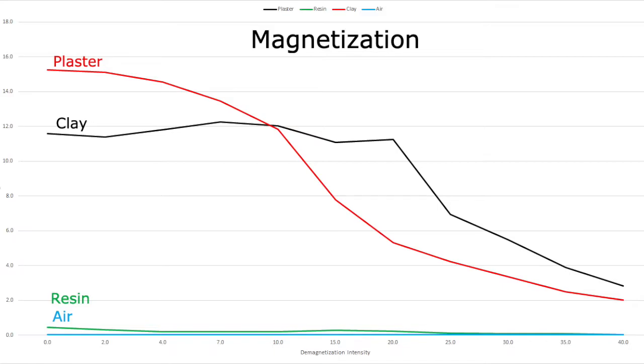Looking at the strength of the magnetic fields of the materials, we can see already that the plaster is many times stronger than the resin. In fact, the plaster is as strong as our clay, and the resin is as weak as air. In other words, as far as the spinner magnetometer is concerned, the clay and plaster look the same, and it's as if the resin isn't even there.